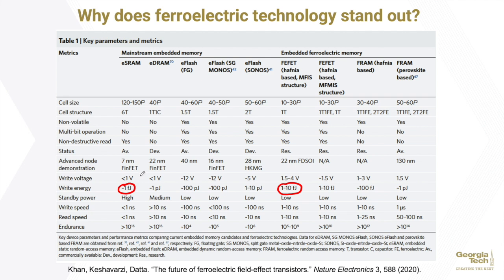On the other hand, compared to the incumbent non-volatile embedded memory technologies based on floating gate transistors, for example, E-flash technologies, ferroelectric field effect transistors can be much cheaper, because to integrate ferroelectric field effect transistors in the front end, you need 2 additional masks only. On the other hand, to integrate the floating gate transistors we need upwards of 5 to 7 additional masks. And as a result, these floating gate transistor based technologies are hitting a wall in terms of economics for high density integration.